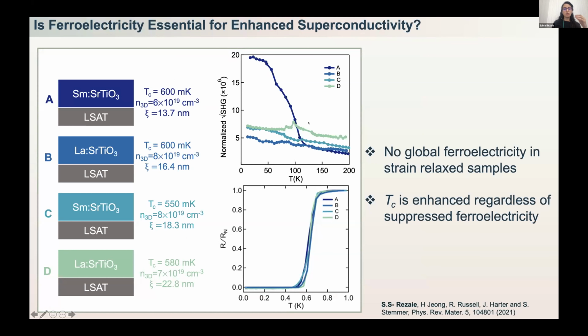But we were able to manipulate the polarization in these structures so that we only have a global ferroelectric transition happening in one of them, here marked as film A. The rest of the films down here, although the superconducting critical temperature is enhanced in all of them, don't have that transition to the global ferroelectric state. With this, we can understand the connection between the enhancement in superconductivity and the domains that might form in this structure.